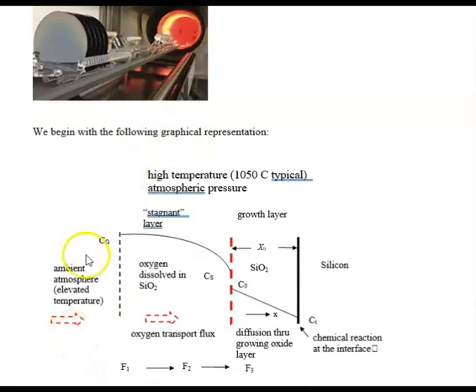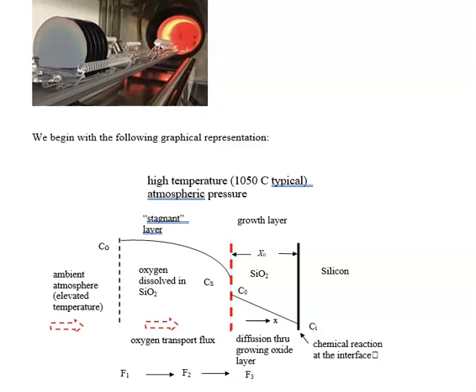We have the atmosphere, this is the ambient out here before we load the wafers. As we load the wafers in, of course, the temperature goes up. So at this point, when the wafers are loaded into the furnace, we still have an atmospheric situation, and we have a concentration which is Cg. So if we look at this a little bit closer, what we have are 4 concentrations. And these C's refer to the concentrations of oxygen. And notice that they decrease as the process moves from left to right.